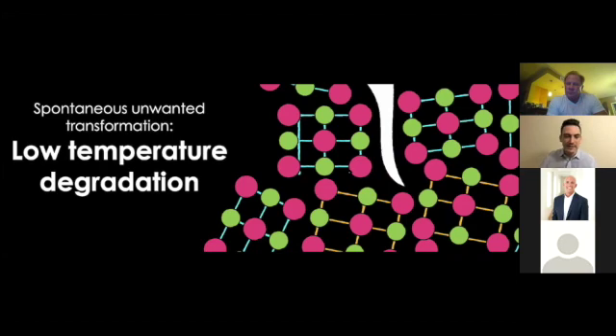And why this got to be such a big deal, honestly, in my opinion, is because in the implant industry, like not dental, in the orthopedic implant industry, they were using zirconia, and there was some company that had this bright idea that they were going to autoclave their zirconia implants before mailing them out. They call it low temperature because this is something that happens in water at low temperatures, which means body temperatures. But if you put something in an autoclave, it will accelerate that process and cause like 100 years worth of low temperature degradation in an hour or something like that. So maybe not that extreme, but it accelerates it.